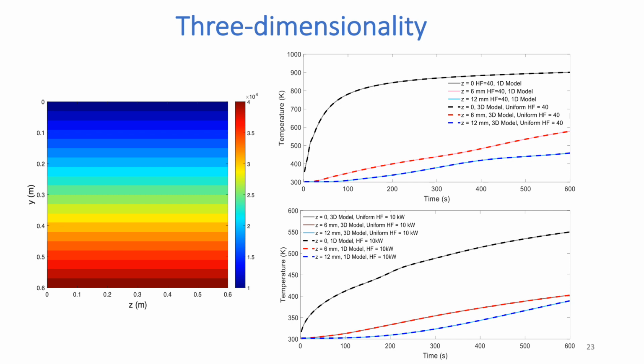We simulated non-uniform heat fluxes, but as we can see, the differences between the predictions from a uniform heat flux and from a varying heat flux using a 3D model, for selected locations, are very similar. That means the problem can be reasonably approximated as a one-dimensional problem. This is because the gradients along the depth are much larger than the gradients along the length and width of the gypsum board. So except very close to abrupt changes in heat fluxes, gypsum board calcination can be reasonably approximated to be a one-dimensional problem.